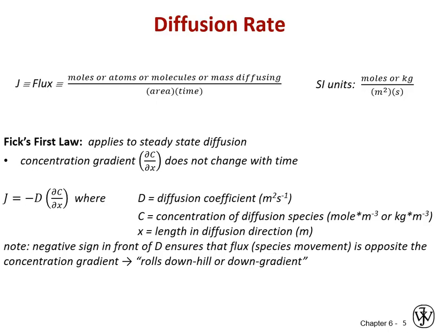This holds only when that concentration gradient does not change with time. Another way of saying an invariant, or not changing with time, concentration gradient is steady state diffusion. So when you hear someone say, this is a steady state diffusion scenario, or this is diffusing at steady state, you know that you can use this very simple relationship.